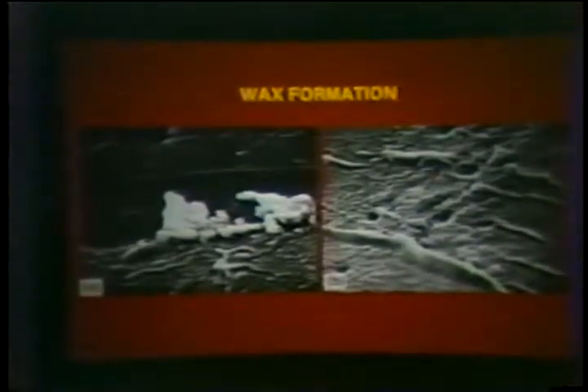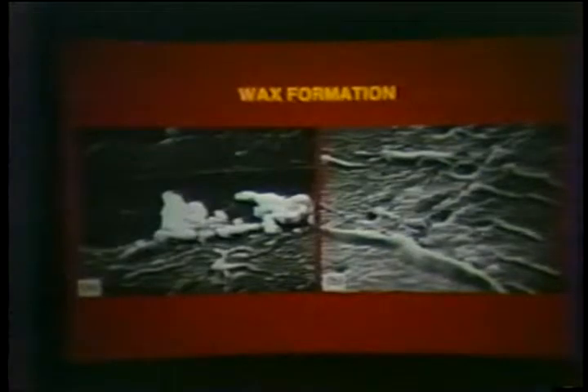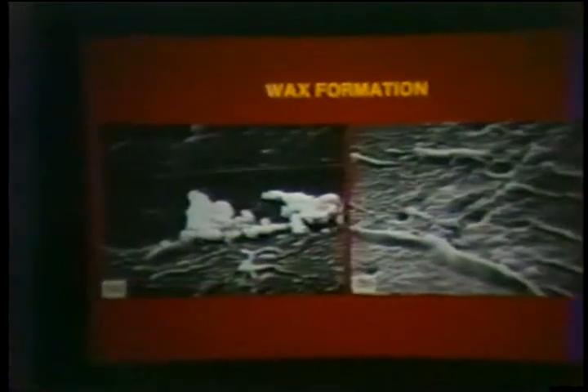In the next slide, we see the effect of partial discharges that can take place within a capacitor roll. Here is a scanning electron microscope picture of the surface of polypropylene film that has been taken from a capacitor after accelerated life testing. On the left, we see the waxy appearance of this material, which we believe to be the fluid which has been converted under partial discharge activity to a wax. On the right, we again see this waxy material with pits present in it, which are caused by repeated partial discharging. Ultimately, this may result in clearings in this area.